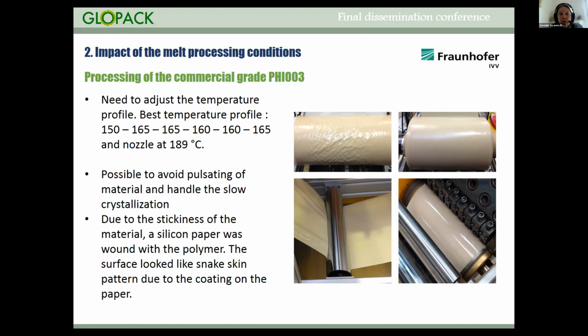But it was possible to extrude several running meters with the commercial grade, and it was also possible to avoid pulsating of the material and handle the slow crystallization. But due to the stickiness of the material, we wound silicone paper between the polymer layers, and therefore sometimes on the pictures the surface looked like snake skin. And you can see here the color of the film. It's beige to brown, produced from the PHI-003 grade.